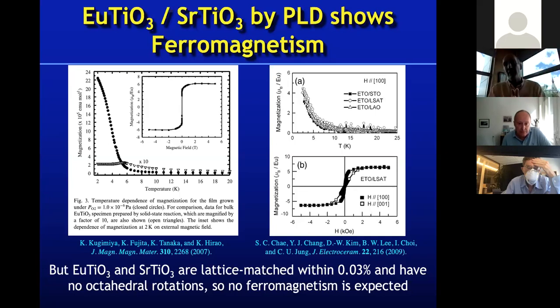I think that what's going on in these results is that because they were growing at low pressure, they had bombardment effects. And I say that because some of these same groups also grew strontium titanate on strontium titanate by PLD. As they go to lower and lower pressure, they see a peak of the strontium titanate film that is not overlapped with the peak of the strontium titanate substrate. So, strain aside, octahedral rotations aside, if it's strontium titanate on strontium titanate and the peaks don't line up, something is wrong. So that's an example of where bombardment can cause issues.